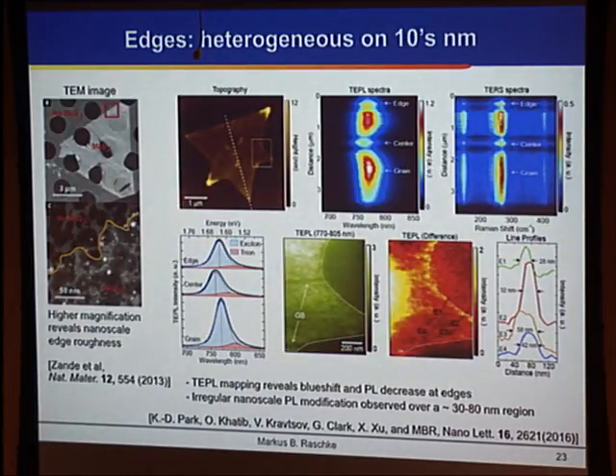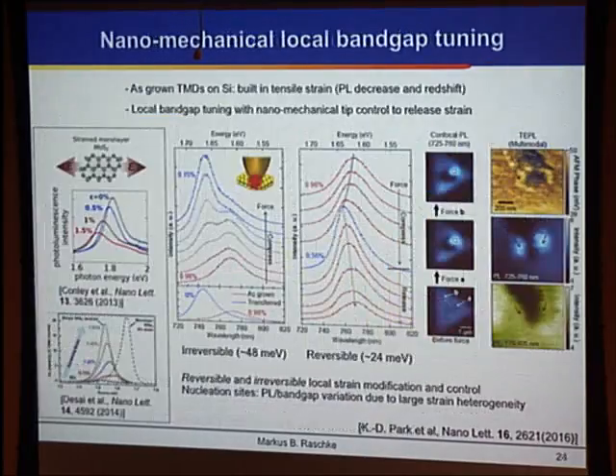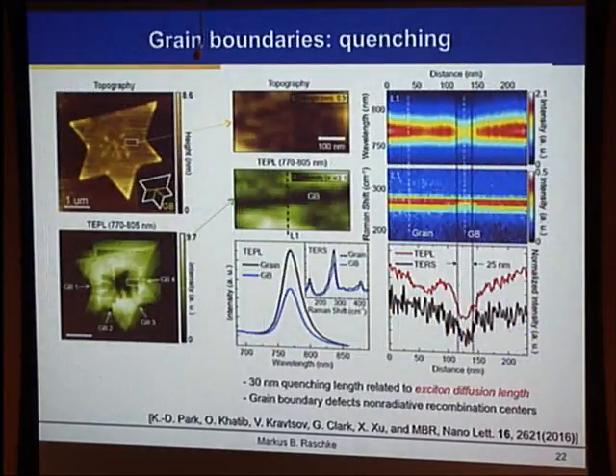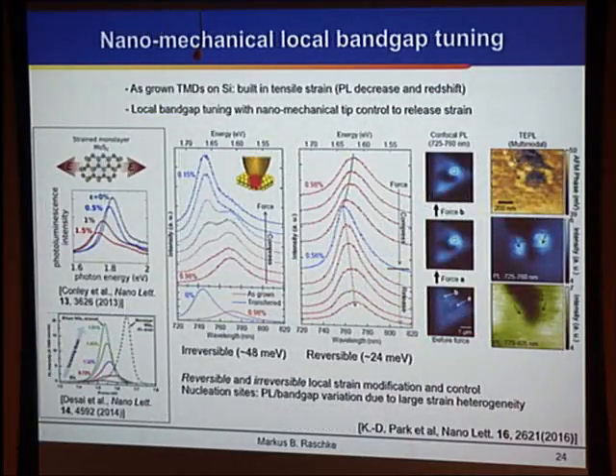And so one can also see this in the corresponding Raman data. One interesting puzzle has always been, let me go back here, that we have this decrease in the photoluminescence at the nucleation site. And to address this is where we resort to this idea that we can now use the tip also as a local force probe and locally control the strain. And so if you start to compress onto that sample region where we have this low emission, then we see a shift of this exciton to higher photon energies as we compress. So as you compress the lattice, right, then you would increase the exciton splitting.